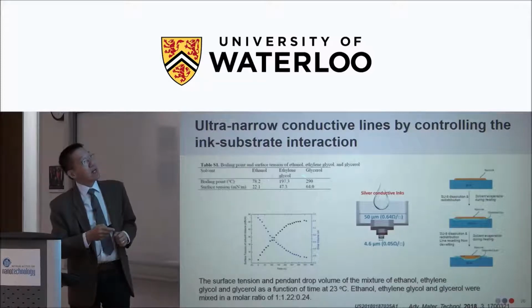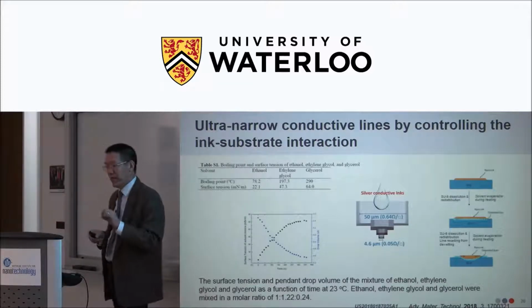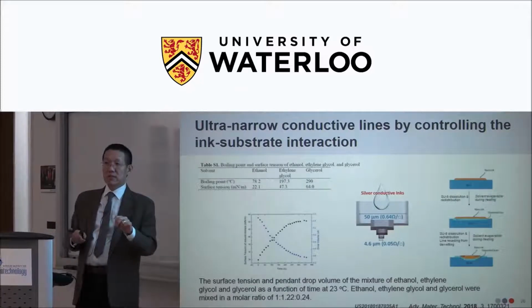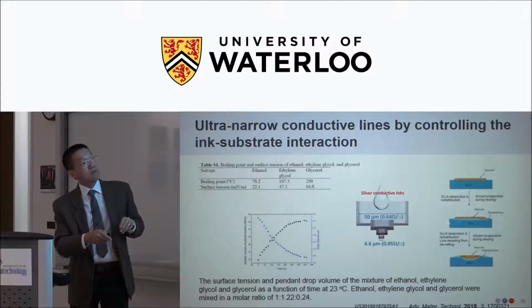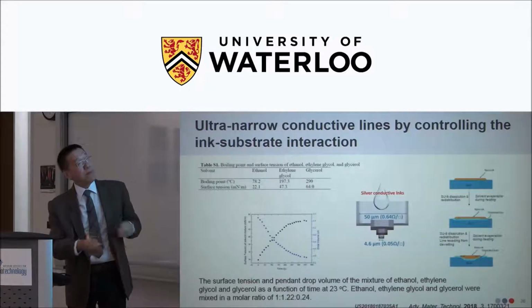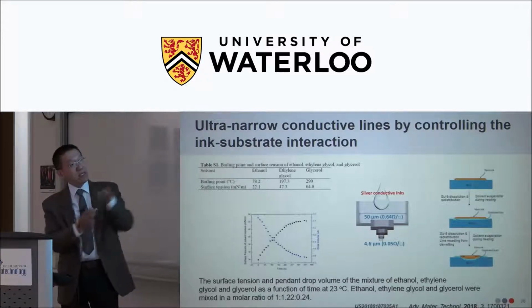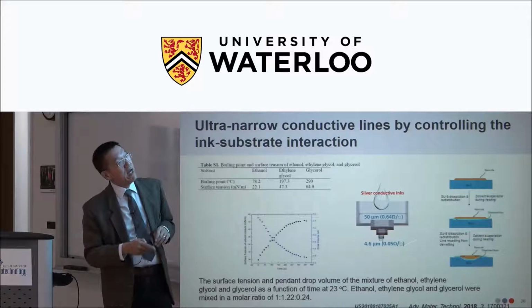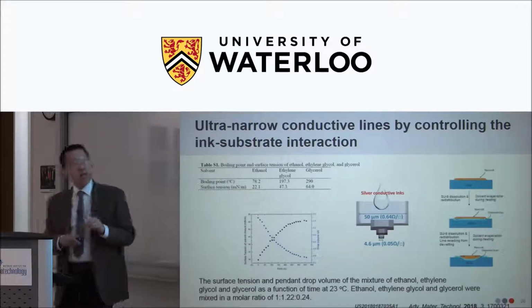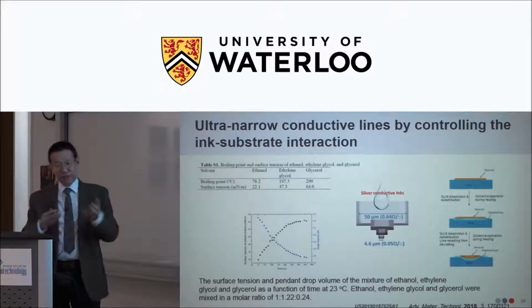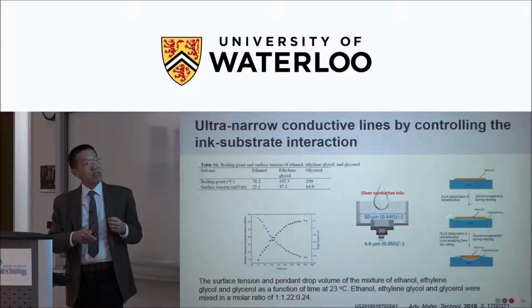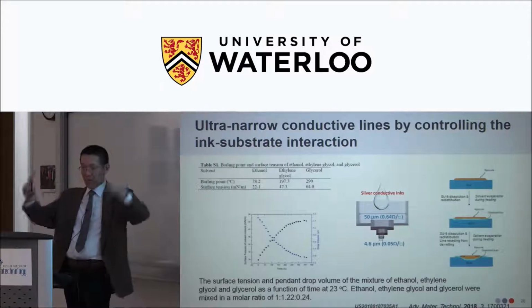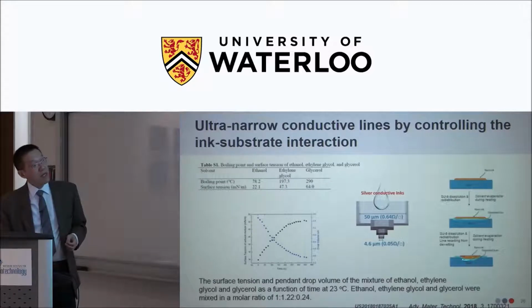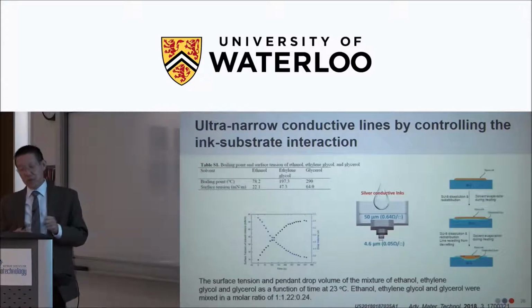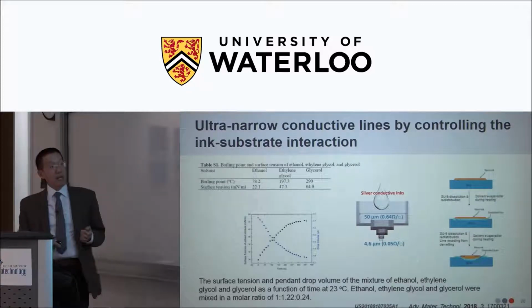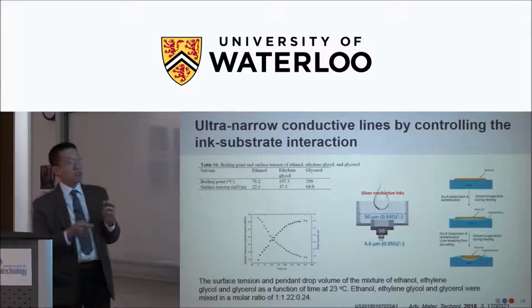At the same time, the ethylene glycol has some capability to dissolve SU8, uncross-linked SU8, this layer. Okay, the blue, yeah. It dissolves the SU8 slightly, so there's an interlayer between the printed silver and the SU8. Now, they're floating. And the ethanol keeps evaporating at the two ends, and you have relatively high surface tension here and there. They pull the liquid out continuously and gradually, and the ethanol keeps evaporating. So the line will keep shrinking during the drying process, becoming smaller and smaller.